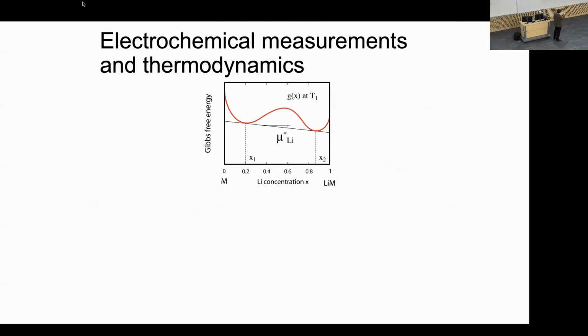Because let's say you have a free energy curve that looks something like this. So M could be something like iron phosphate, and then this is lithium iron phosphate, and this is the lithium composition axis. And I think most of you are probably able to read a free energy curve like that. You know that if you're somewhere between X1 and X2, this would be the free energy of a homogeneous mixture, but that's higher than a two-phase mixture, which has a free energy lying on this common tangent. So between X1 and X2, you want to phase separate.